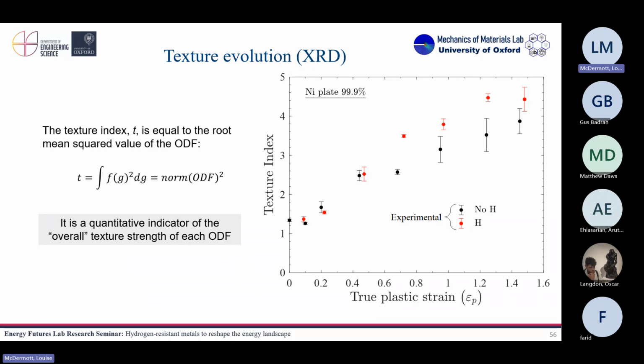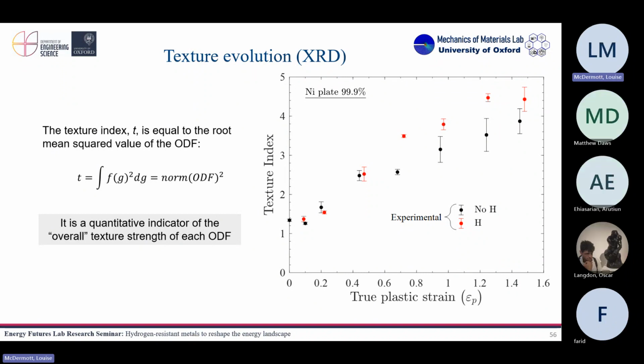From that point, there seems to be an effect of hydrogen on texture evolution, which would imply that there is an effect of hydrogen on plasticity. In this case, the texture evolved faster in the hydrogen-charged samples, so hydrogen is enhancing dislocation evolution in this sense. However, even though we have around 200 measurements in this figure, so it's a lot, we still want more robust results, so we can really make a statement and say, okay, hydrogen is doing this on plasticity.